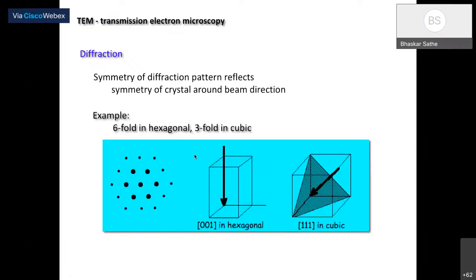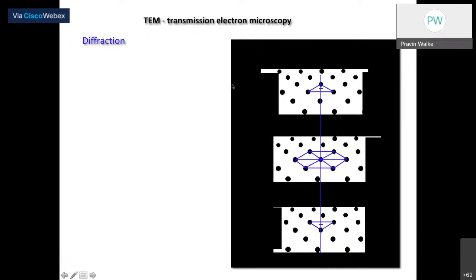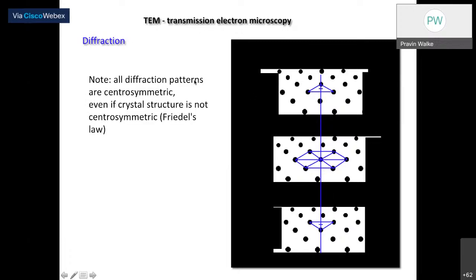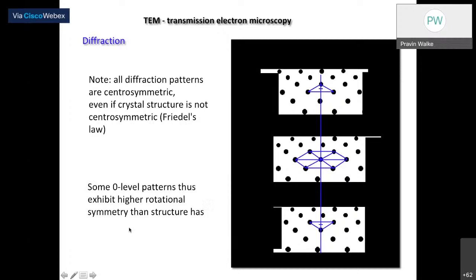Okay, so let's have a look at the diffraction pattern. The symmetry of the diffraction pattern usually reflects the symmetry of the crystal around the beam. Usually 6-fold in hexagonal and 3-fold in cubic. Here you see the hexagonal and cubic. But the question arises, why does the 3-fold diffraction pattern look like a hexagonal one, right? That question needs to be answered. For example, here you see the different patterns, and usually all diffraction patterns are centrosymmetric, right? Even if your crystal structure is not centrosymmetric, your pattern is centrosymmetric, and that was given by Friedel's law, right?